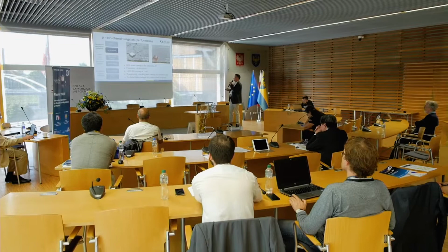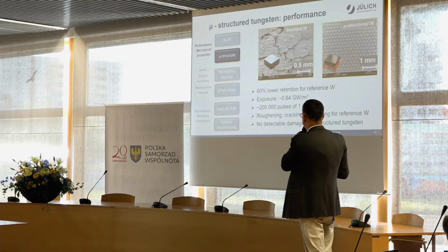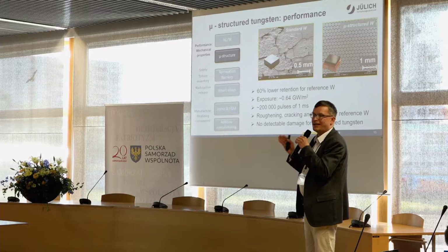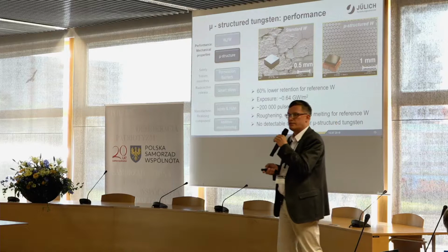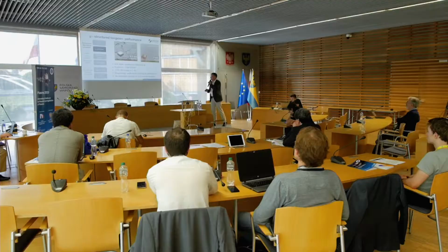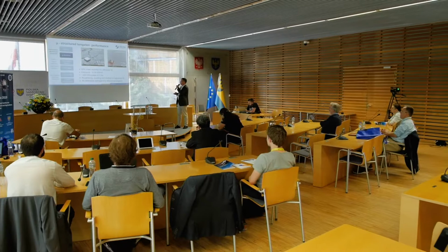And the standard tungsten, which is shown here on the left-hand side, you see the cracks appeared after already a couple of hundreds of cycles and started to propagate. And still, after 200,000 cycles, we don't have any detectable damage on the macrostructures, which is terrific performance, I tell you. These are the solutions or concepts for the loaded areas for the normal, regular plasma operation of